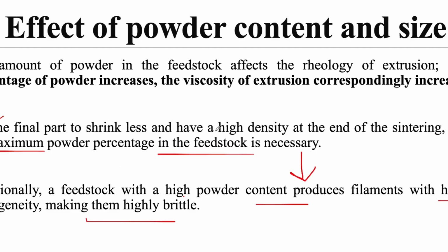So if you read these two points, they are contradicting in nature. In the second point, I am telling you that if you want very little shrinkage, use maximum powder. While in the third point, I am telling you that if you use the maximum amount of powder, it will make the filament very brittle. So that is the reason you have to make a good balance of these two things. There is an optimal concentration of powder that you need to find out and use for your filaments. The rheology is of course very, very important. The viscosity is very, very important to look into when the filaments are being fabricated.